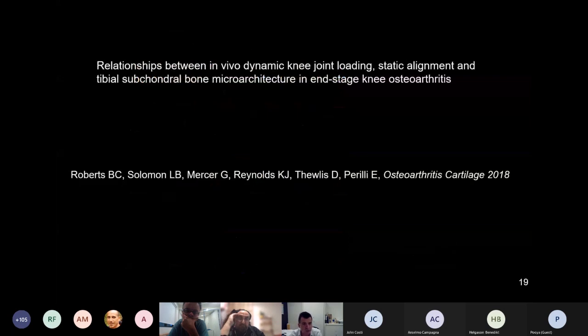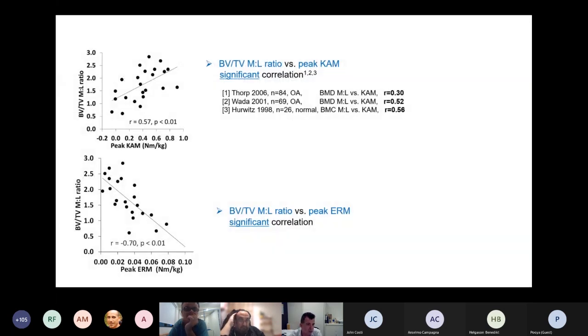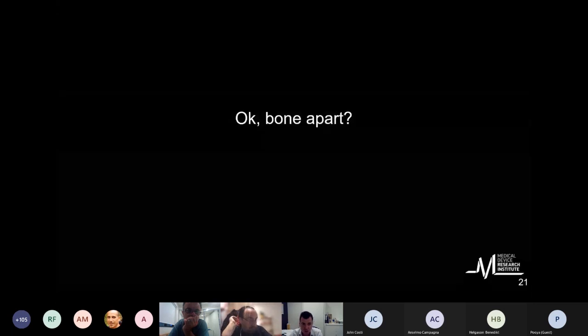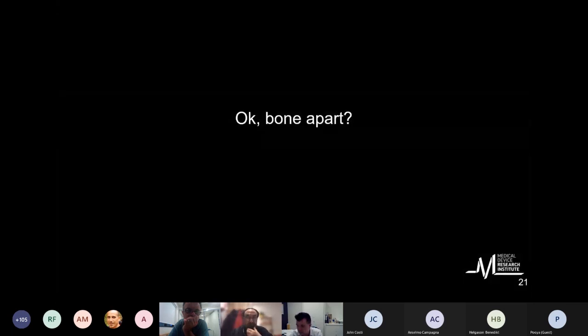So we combined this with gait analysis, and what was found is that the knee adduction moment correlates positively with the medial to lateral bone volume fraction, and the peak external rotation moment with the medial to lateral bone volume fraction ratio. So there is something there related to gait and to joint alignment, which we can look into. And so that was the bone.